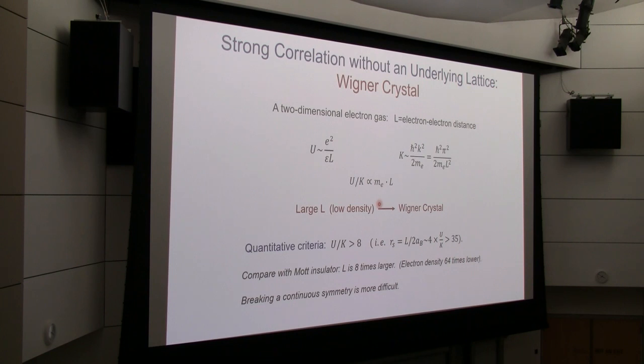A very common parameter people use in the literature is known as rs, which is defined as electron separation divided by 2 times the effective Bohr radius. So it's related to U over K. And in that case, that number has to be larger than 35. So these two are equivalent.